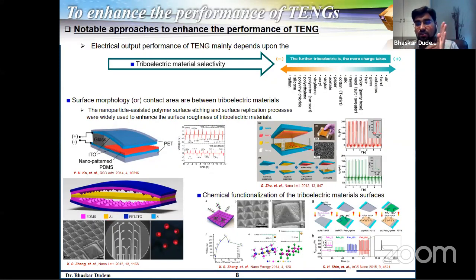How could it be? When we introduce nano or micro architecture on top of the surface of the triboelectric material, it can give a high contact area between the two materials. And increasing the contact area is going to increase the surface charge density, which results in a very high electric output. So creating nano or micro architectures on top of one or both of the materials is done by different techniques like lithography and dry etching techniques.